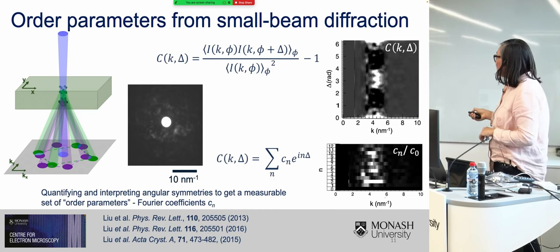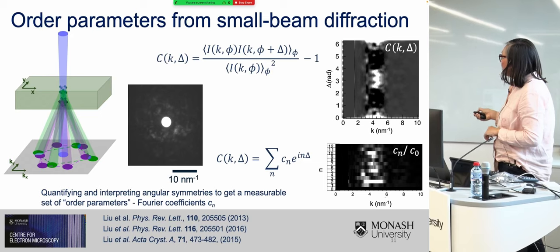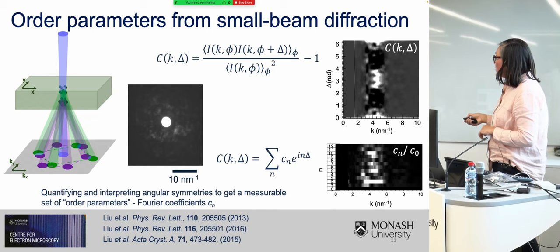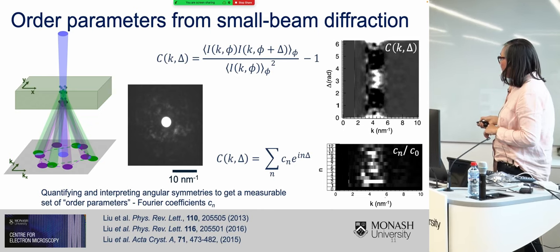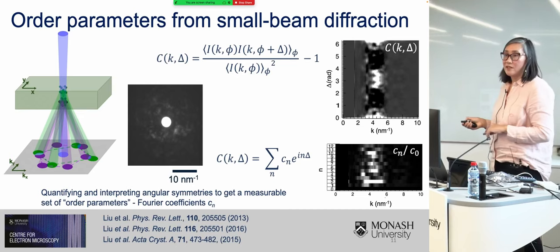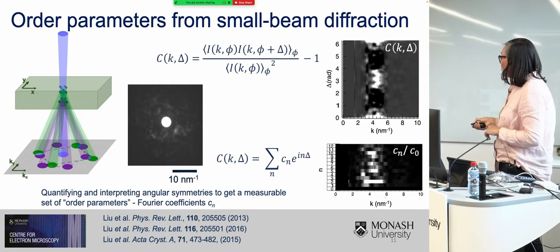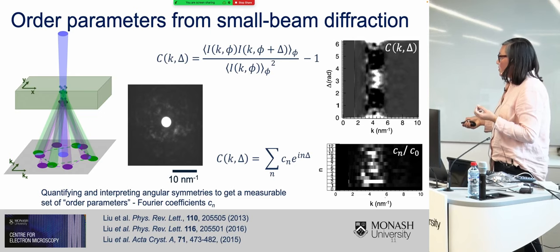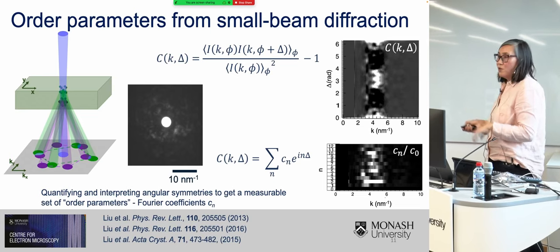To quantify this even further, I fitted this angular autocorrelation function at every value of k with a Fourier series and obtained the Fourier coefficients of each of my symmetries. This is what I'm displaying down here. You can see that, yes, in this area of the first sharp diffraction peak, we have some very prominent angular symmetries that we're extracting using this method. Going forward, I average these coefficients over the region corresponding to this first sharp diffraction peak, and I call these my symmetry magnitudes, order parameters, or Fourier coefficients.